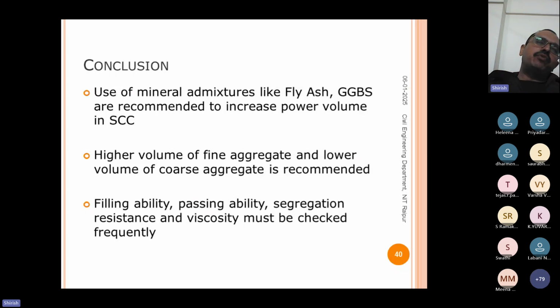To improve the workability and the viscosity, we need to use fly ash, GGBS, and similar materials which are useful in enhancing the workability of concrete. We have to use a higher volume of fine aggregate and a lower volume of coarse aggregate for producing self-compacting concrete. The concrete which is produced should have filling ability, passing ability, segregation resistance, and viscosity.